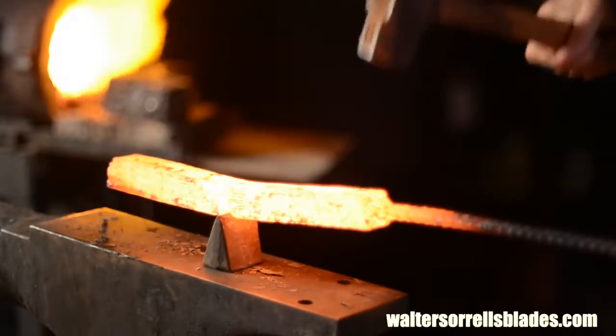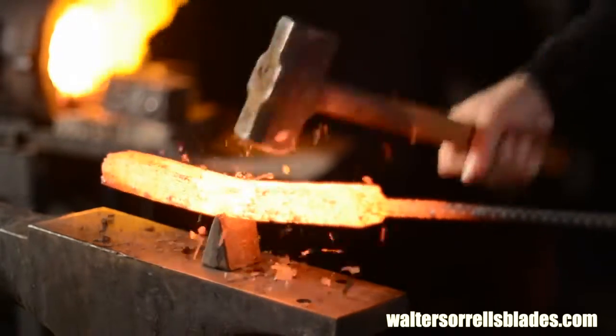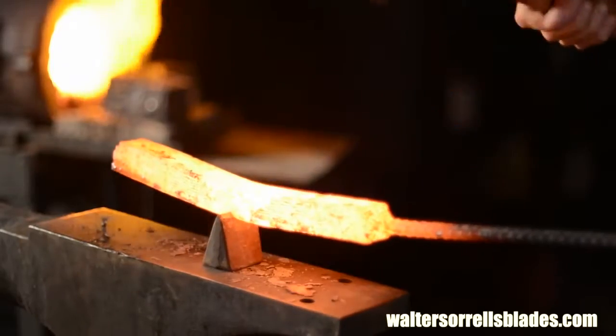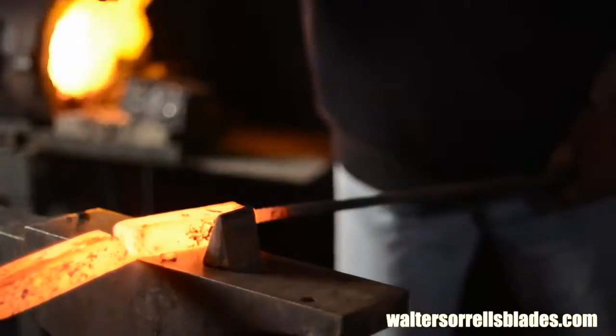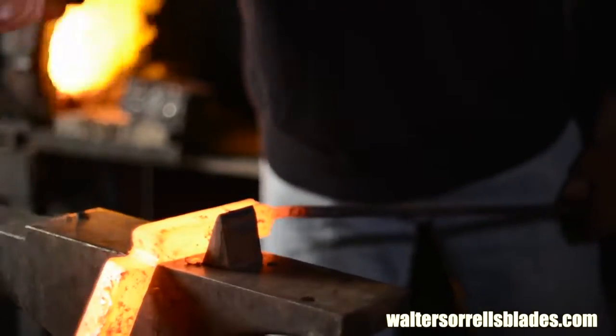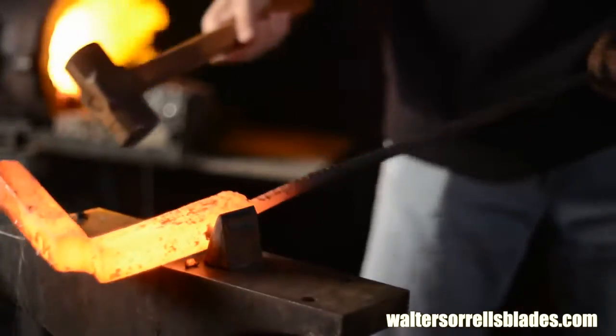Actually, you don't cut the billet all the way through. Instead, you cut it almost in half, leaving a thin web of steel where you cut. Too thin, it breaks in half. Too thick, it won't fold over. 1/8 of an inch is about right, give or take.